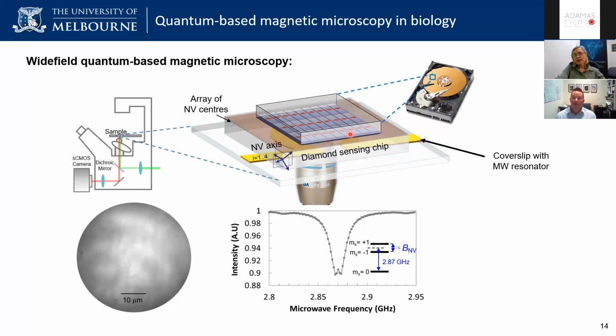Yeah, so I think patterning is really good when you're trying to understand how the signal would change with different implantation parameters and things like that. For us, we've found that these 4 keV implants at 10^13 provide decent T1 and ODMR properties to image. So our preference is to make the whole chip sensitive, so whatever sample we put on top, we can image anywhere in that sample and it's going to be the same.